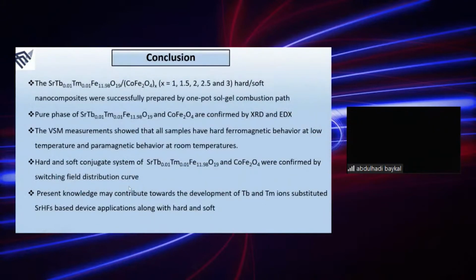In that case, we tried to synthesize the nanocomposites, given in this formula as hard-soft nanocomposites, and they were successfully prepared by one-pot sol-gel combustion. This is important because in some cases they prepare the hard and the soft separately, and then do physical mixing to produce this compound. But this way has some disadvantages. In our case, by using the one-pot sol-gel combustion pathway, with the help of one run, it was possible for us to successfully synthesize all these 5 compounds.